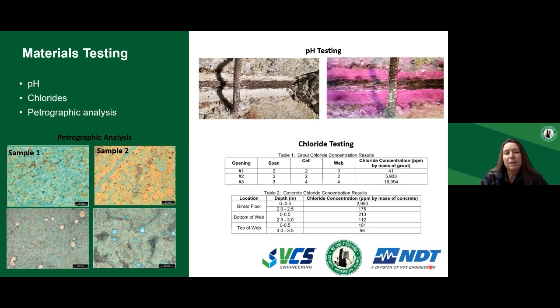pH testing is typically done at large openings where a section of the duct is removed to expose the grout. You can use a rainbow indicator solution, which changes color depending on the pH range, or you can use a phenolphthalein indicator, which is what you see in this photo. The phenolphthalein indicator changes color to pink when the pH of the grout is above 9.5, and if it's below 9.5, it remains colorless.